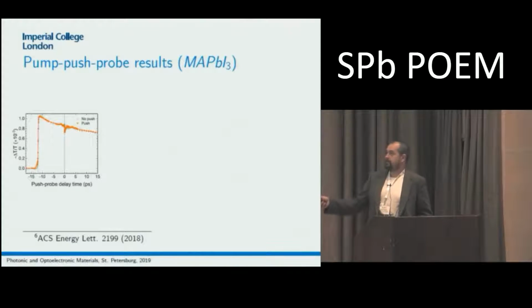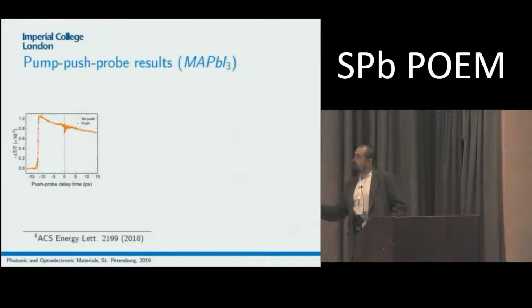This is just an experimental signal that we can see. This is optical pump infrared probe. This is not a terahertz measurement, but I'll talk further about how this can be used. So first we pump at really low powers, so as not to have Auger processes, but we have excess energy. Then when the push arrives, we have a drop of signal, and then recovery of the signal to the normal curve. These points correspond to the same pump conditions with push and with no push, and we can see that the curve is similar, and push affects only this part of the signal.